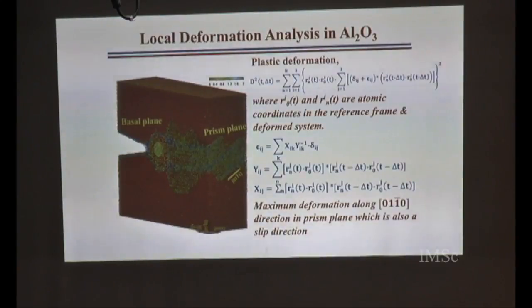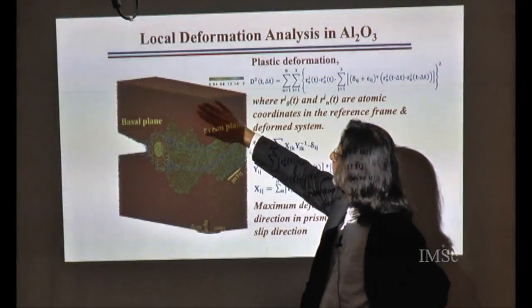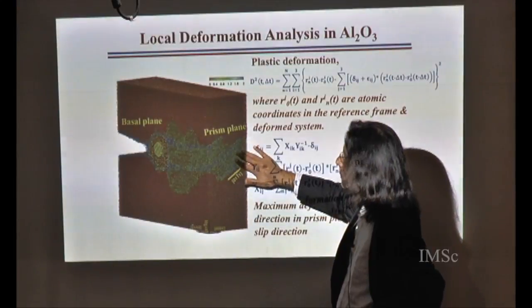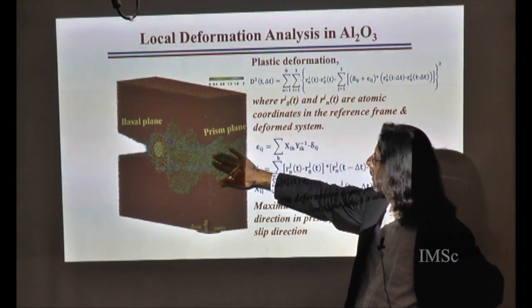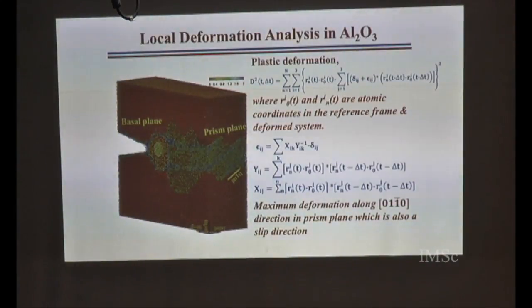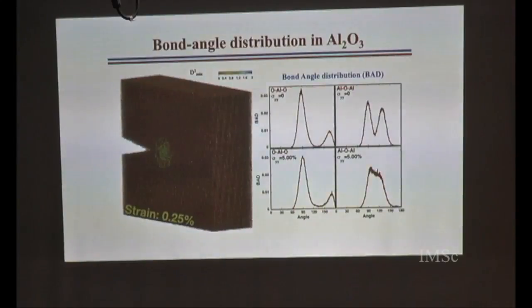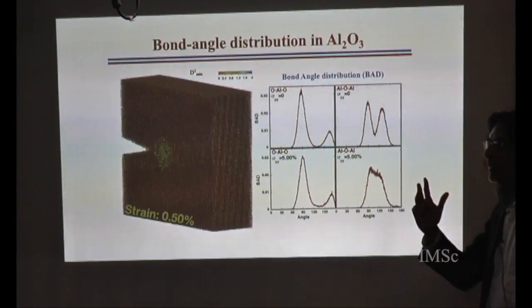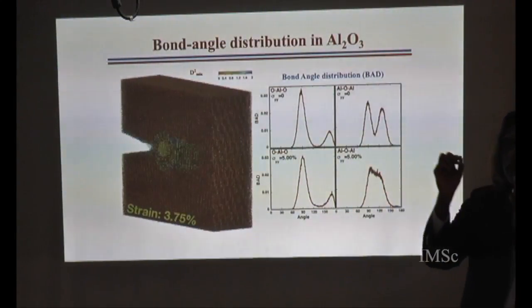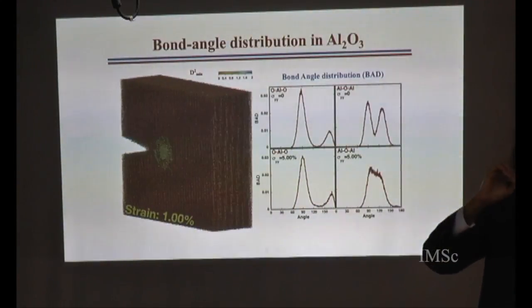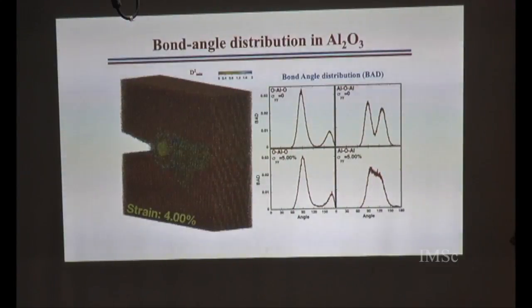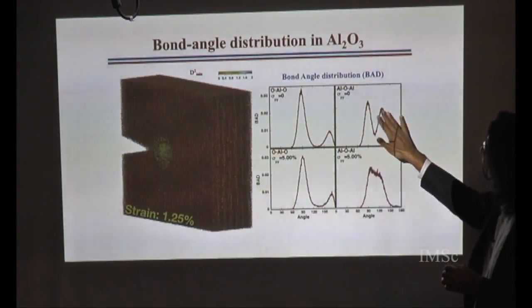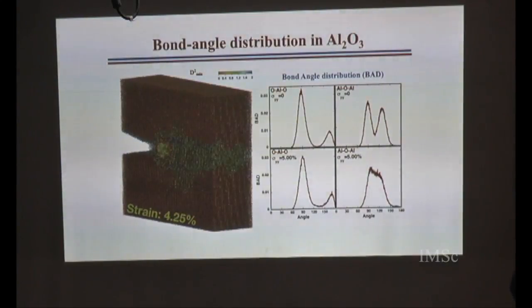Again, we did local deformation analysis, and this picture shows the pristine alumina matrix, and the damage is in this region. This is the local deformation analysis, and this is the damage part. What we found was that certain things change in the damage zone, but not a whole lot. One thing that changes is the aluminum, oxygen, aluminum bond angle: an aluminum-oxygen bond, and then you pick another aluminum. This angle is the one where we see major changes. As far as the lattice is concerned, in the damage zone is where bond angles are changing.